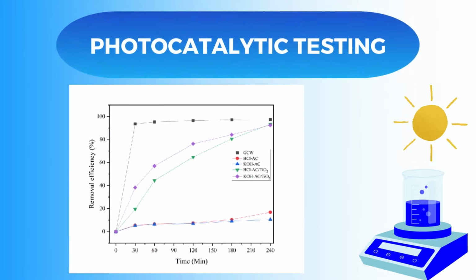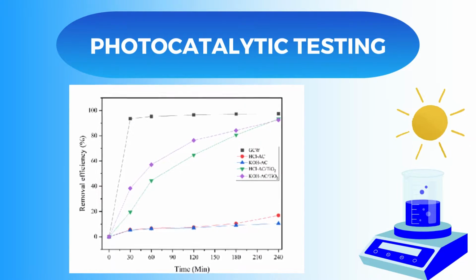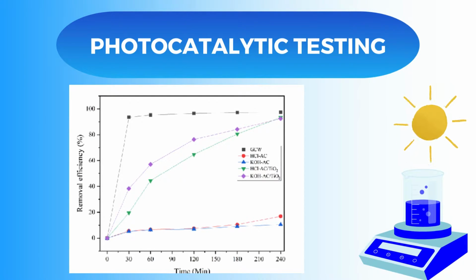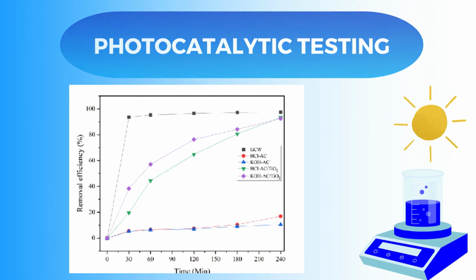For the photocatalytic testing result, ground coffee waste exhibited the highest removal efficiency. This is due to the presence of a large number of carbonyl and hydroxyl groups that contribute to higher adsorption capacity for cationic dyes, due to its highest average pore width. Two mechanisms occur, namely adsorption and photocatalytic degradation. Adsorption occurs in samples without TiO2 photocatalyst, while photocatalytic degradation occurs in samples with the addition of TiO2 photocatalyst. Under sunlight, TiO2 is a semiconductor and also enables photodegradation, which can improve the methylene blue removal.